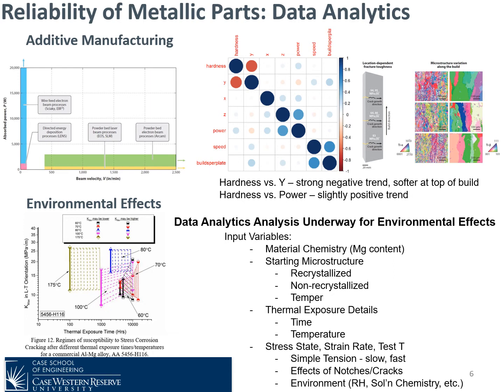And through that analysis, preliminary work now, hardness was very strongly negatively correlated with height, meaning the material got softer as the build got taller. And that correlates pretty well with some of the other things we've seen, both with regards to the microstructure and the properties. Hardness versus power also had a slightly positive trend in this case.